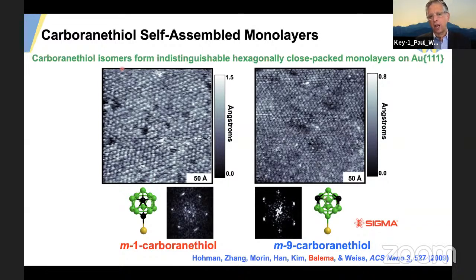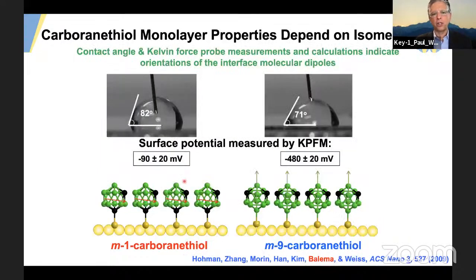And you can see it's even difficult to identify where the domain boundaries are, because the only kind of boundary one gets in a complete monolayer is an offset in registry that's either translational or rotational. There are actually 5 domains here, and we've developed mathematics to determine those automatically. Okay, and we can show on the nanoscale or the macro scale the charge on these surfaces.